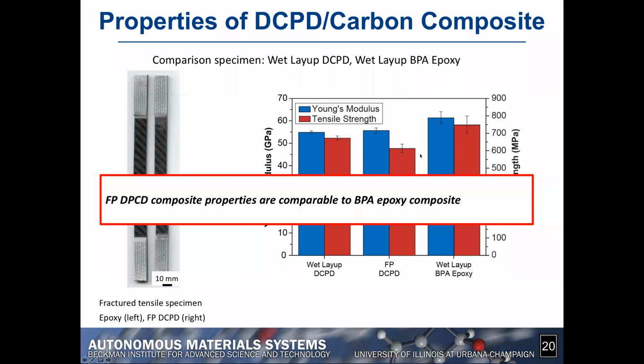However, it's important to remember that carbon fibers have been optimized through a series of sizing systems to interact with epoxy. We use the same fibers, so we have not really optimized the interface yet, and that's part of the current research activities. The objective is really to find the treatment of the carbon fibers that will strengthen the bond between the carbon fibers and the DCPD.